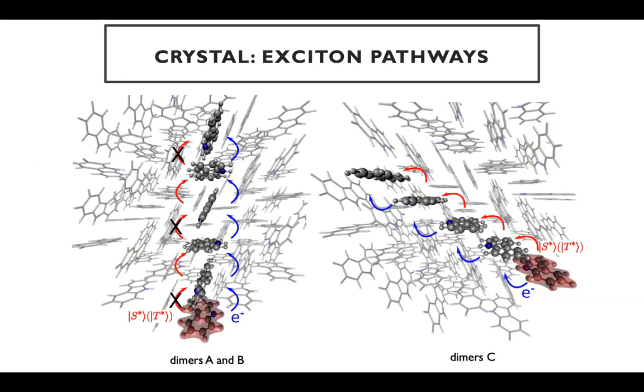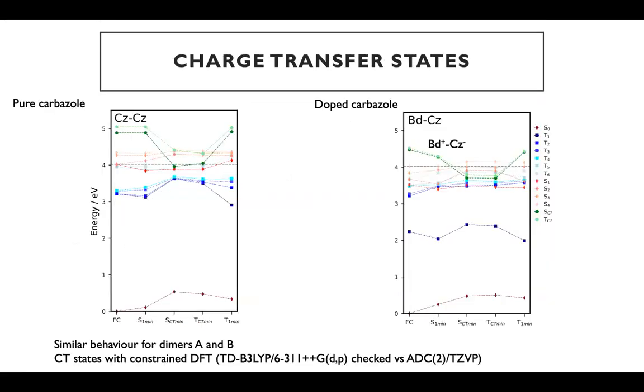However, if the lifetimes of the triplets are a little bit longer than singlets, the process could still be important here. So if we try to put all of this information together, we can propose what the exciton pathways may be in these crystals. You can see that the excitons will follow pathways through dimers A or B, or you will also find an exciton transport pathway along a linear line of C dimers.